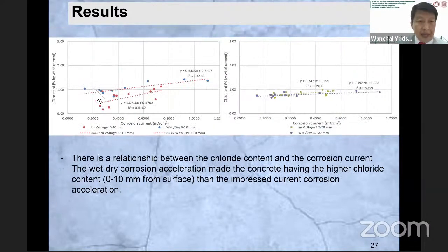And also, this graph shows the relationship between chloride content and the corrosion current. There is a relationship between the chloride content and the corrosion current, and the wet dry corrosion acceleration made the concrete have the higher chloride content, at 0 to 10 millimeter from surface, than the impressed current corrosion acceleration.